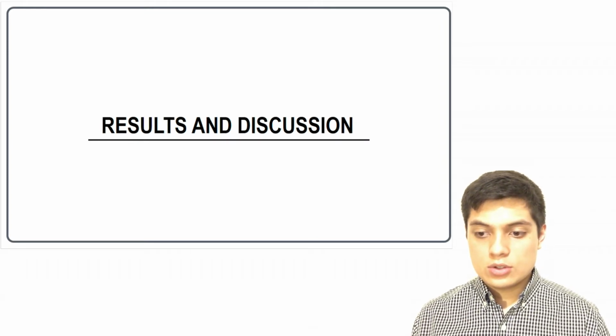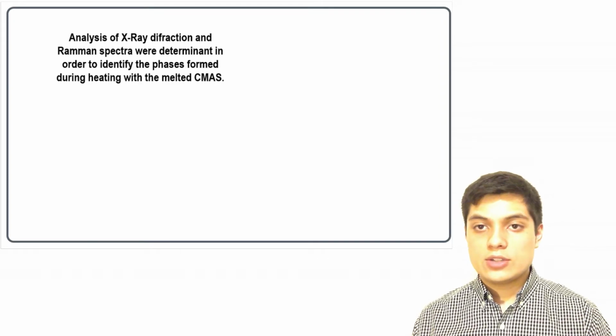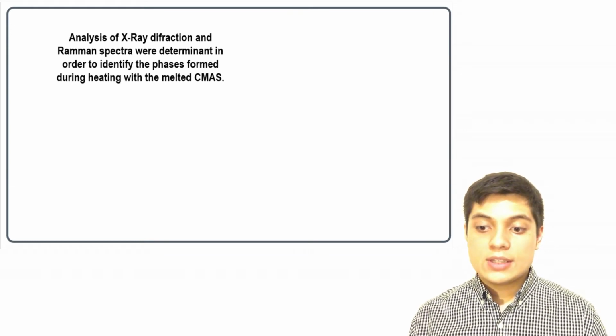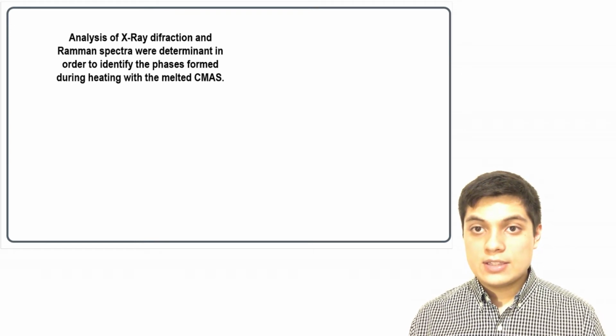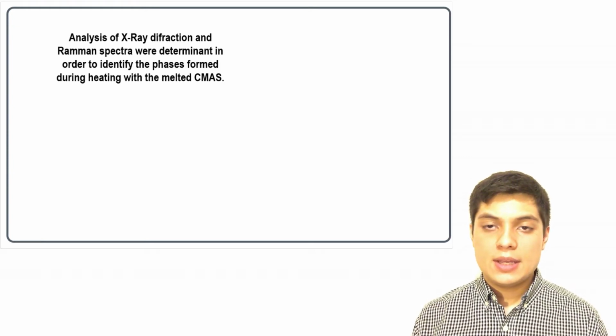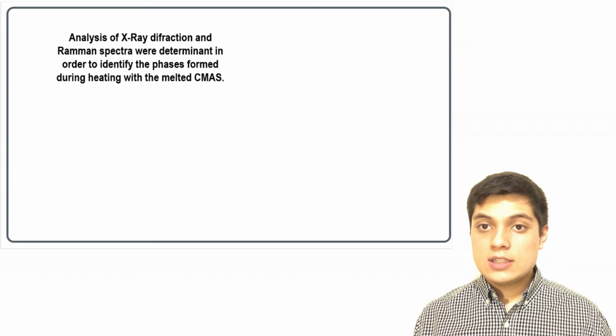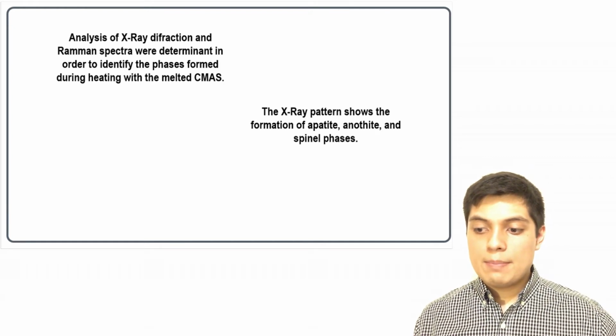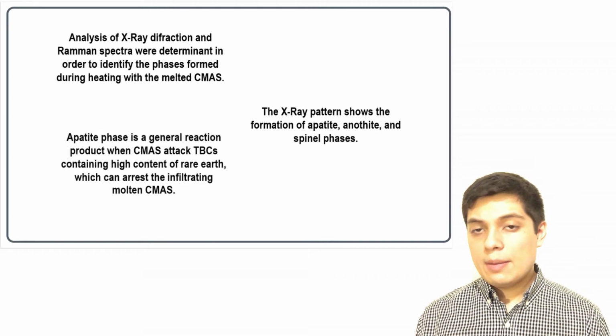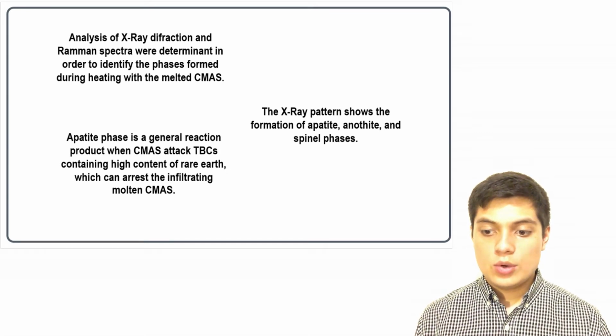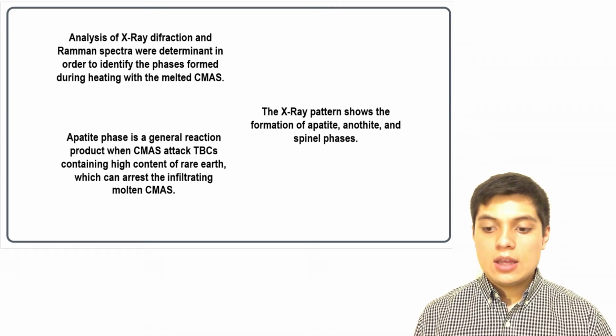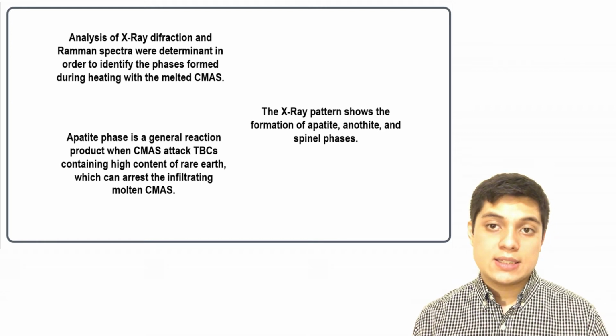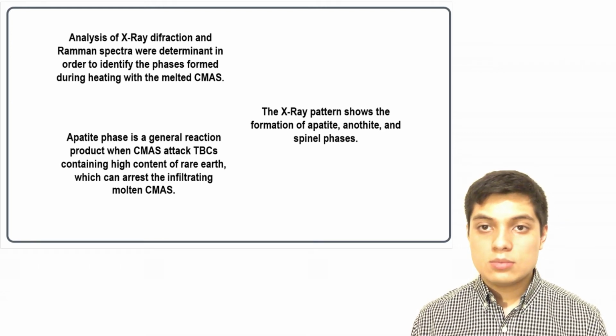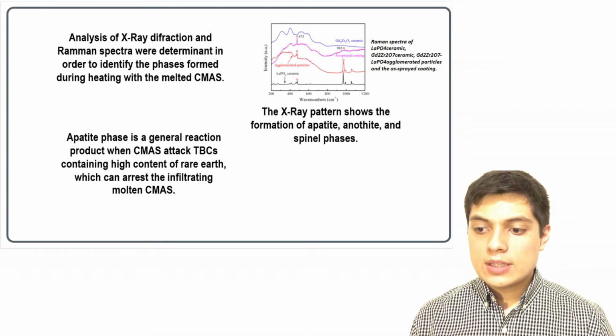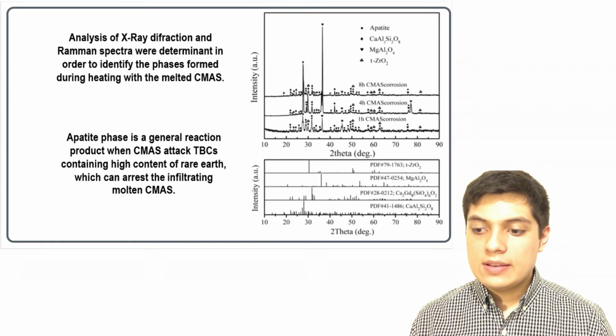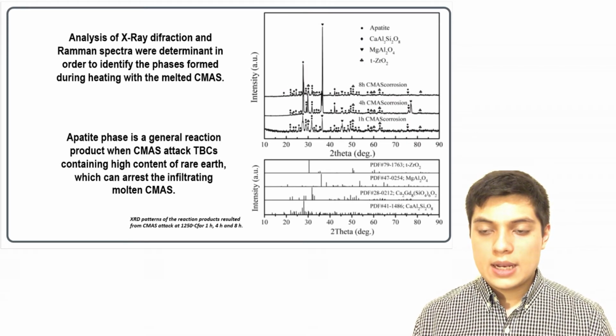The results and discussions. First of all, the analysis of X-ray diffraction and the Raman spectra were determined in order to identify the phases formed during heating with the melted CMAS. So the phases basically consist of an apatite, anorthite, and spinel. And the apatite phase is a general reaction product when CMAS acts on TBCs containing a high content of rare earth, as is our case with a high content of gadolinium. So here we can see the Raman spectra and then the X-ray diffraction pattern.